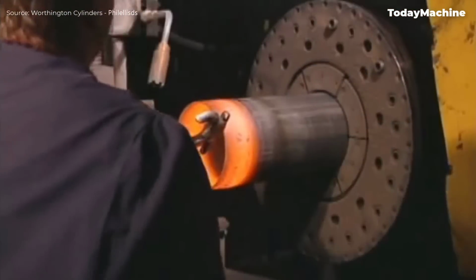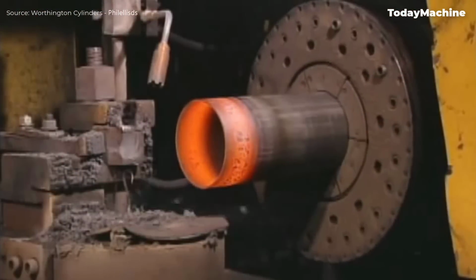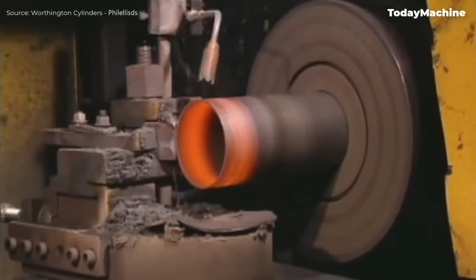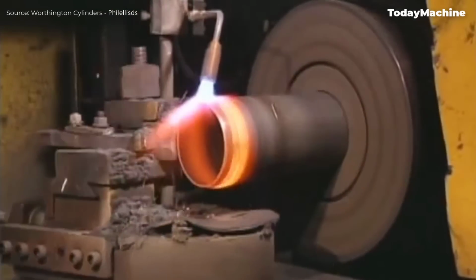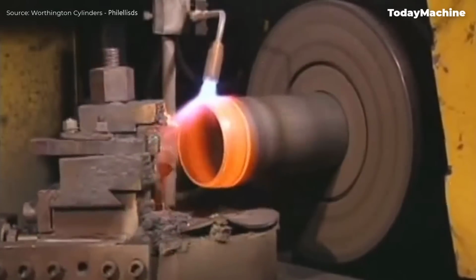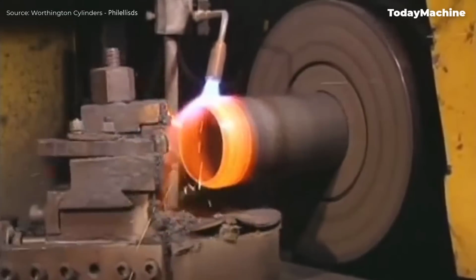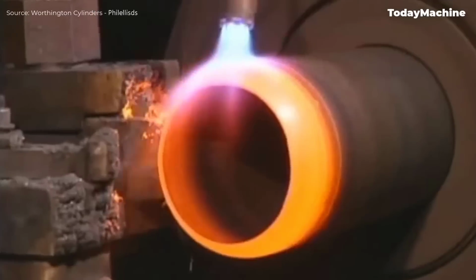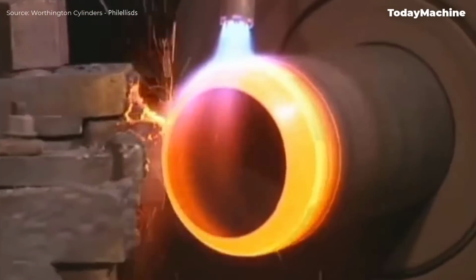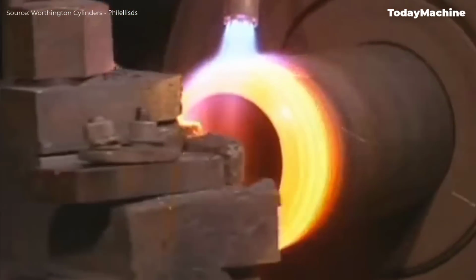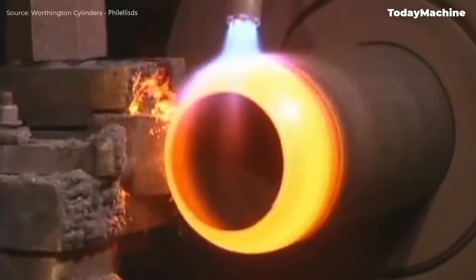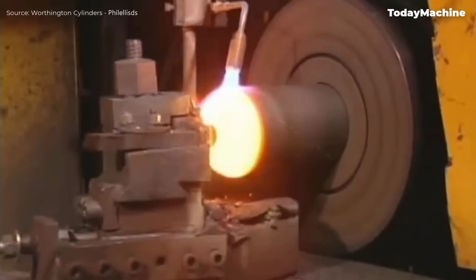In this process, an oxygen fuel gas torch heats the cylinder shell's open end to around 1,600 degrees Fahrenheit. The cylinder is then placed into a spinning lathe, operating at approximately 1,000 RPM, where CNC technology controls the forming of the shoulder and neck areas. The shoulder profiles are typically hemispherical, with a thickness 2 to 3 times greater than the sidewall thickness near the neck.